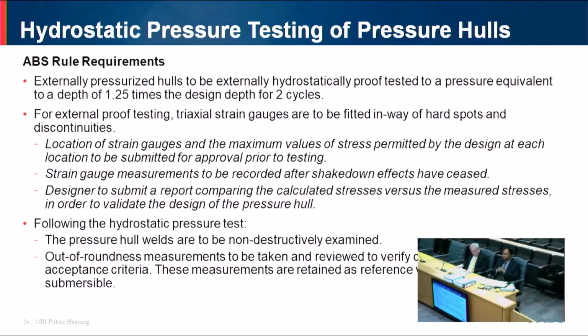And then once the hydrostatic pressure test is completed, you'll have non-destructive examination of the hull. So this is done by surface NDE techniques such as magnetic particle testing, dye penetrant testing, or eddy current testing, okay? And then out of roundness measurements are taken, and then we verify compliance with the acceptance criteria in the ABS underwater rules, okay? Now these out of roundness measurements after hydrostatic pressure testing are used as reference measurements throughout the life of the submersible, okay?